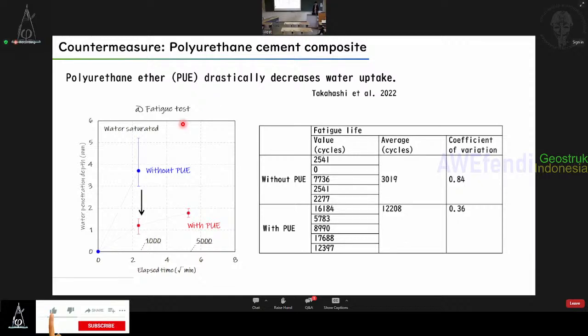And then in that case, I tested with underwater fatigue, and that test was successful. So if you do not add polyurethane ether to the cement or mortar, water uptake during the fatigue test was very high, but if you dose polyurethane ether, the water uptake will be maybe half or less than half. And that could be the main reason for the enhanced fatigue life with the presence of polyurethane ether like this.